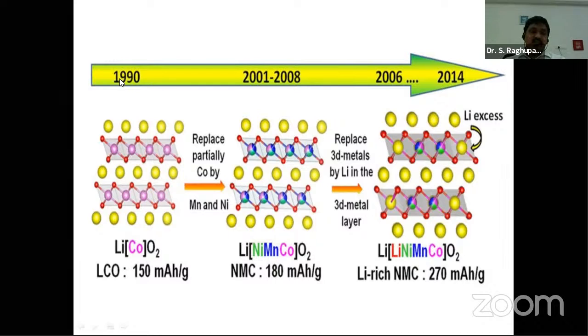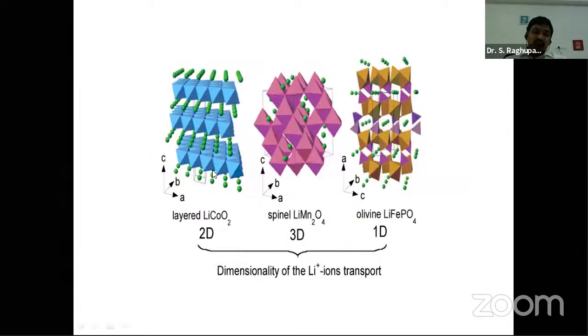LiCoO2 was invented in the 1990s. Later, cobalt was replaced by nickel and manganese, and they achieved a capacity of 180. In recent years, in addition to nickel, manganese and cobalt, lithium is also substituted in that site, and we are getting almost 270 milliampere hour per gram capacity. And here we can see the materials. LiCoO2 is a layered structure, and in spinel LiMn2O4 we can insert lithium three-dimensionally and extract it. In LiFePO4, only along the b axis can you insert and extract the lithiums.